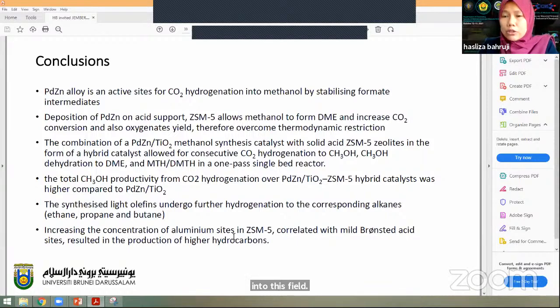The reason why it's very active is because it has this ability to stabilize formate intermediates. And then the deposition of palladium zinc alloy on acid support ZSM5 allows us to actually tune the selectivity of the catalyst. Instead of producing methanol, we shift the activity to produce dimethyl ether, and then it increases the CO2 conversion into oxygenated yields. And then the combination of palladium zinc on titanium as a methanol synthesis catalyst with ZSM5 zeolite as a hybrid catalyst actually allows a consecutive CO2 hydrogenation to methanol, and also methanol to dimethyl ether, in one single bed reactor.